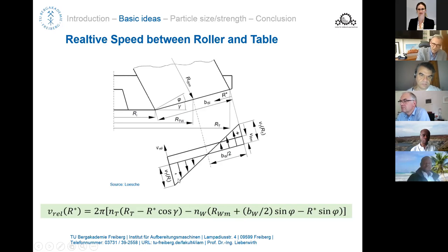So you have in the gap a shear between the roller and the table, which is helping you to produce finer material compared to the HPGR. Of course, at the expense that you have additional wear in these machines. So with this particular roller design, with these conical rollers, you have the chance to adjust this speed at a certain point. You may even reach the area where you have no relative speed. That is possible when the central line hits the central axis of the table at this point in particular. Then it works. You have no relative speed.